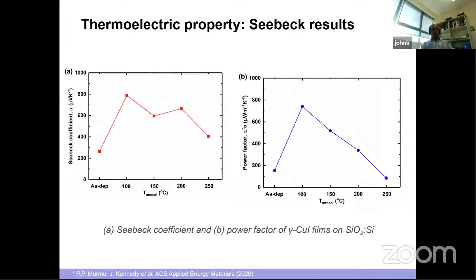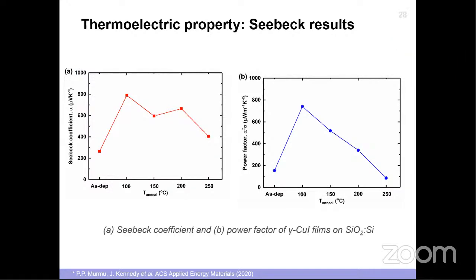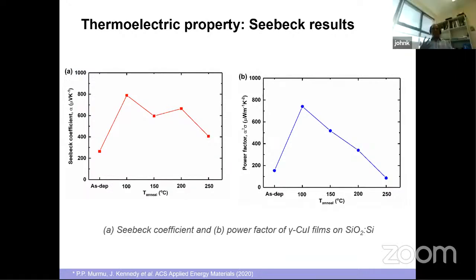We did the Seebeck coefficient measurements and Hall probe experiments. Again, as I said, the Seebeck coefficient and electrical conductivity are related to the power factor. You can see there is around a 300% increase at around 100-degree annealing. Which means if the temperature gradient is somewhere between room temperature and 100 degrees, you can actually convert it into a voltage. So that's promising.